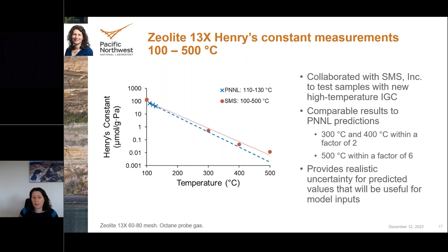And then further, this highlights the ability to extrapolate measurements at different temperatures, but also that it's important to keep in mind that there could be material changes at higher temperatures. So you can extrapolate, but of course it's always best if you are able to make the measurements at the temperature of interest.